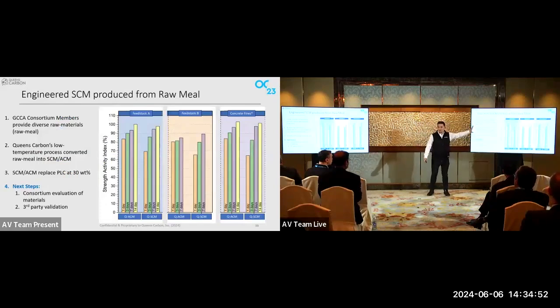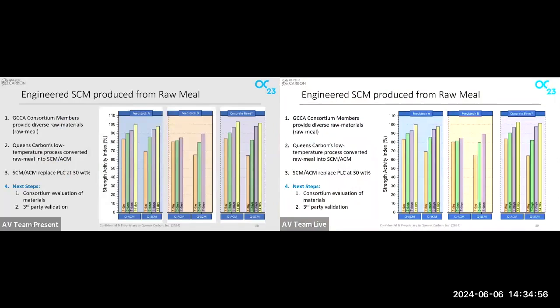A few of the performance data can be seen here. ACM refers to the hydraulic material. SCM refers to the more pozzolanic material. In all cases, the performance is very satisfactory, and in most cases exceeding that of fly ash. So we have good early strengths, and we approach 100% for every single mixture.